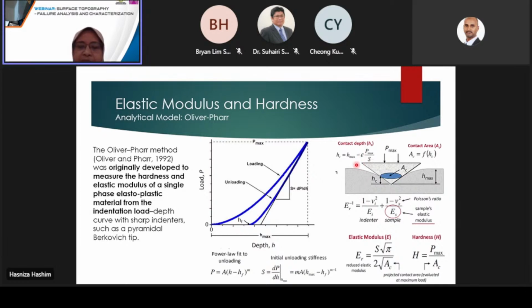HC, the contact depth, is equal to the max depth minus the max force times epsilon, which is some geometric constant depending on the indenter tip installed, divided by the stiffness. The modulus measured in nanoindentation is specifically called reduced modulus, or ER. The relationship between reduced modulus and the Poisson ratio of our indenter, in our case a diamond probe, and the unknown modulus and unknown Poisson ratio of a sample is shown via this expression.